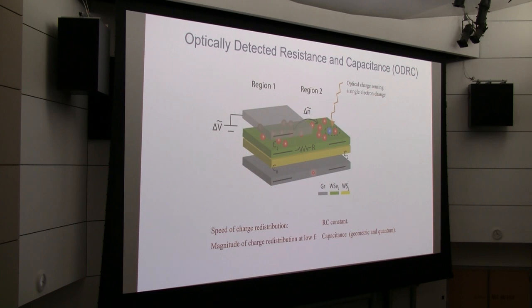And the idea is like this. We have two layers of transition metal dichalcogenide Moire superlattice, and we have both a top and bottom gate. The contact in the system is very bad, so it's hard to do transport, but it's still fine for us to just gate the material and change the carrier density. So once we can vary the density, and we have this partial top gate, what we can do is apply AC voltage to the top gate. As a result, because of capacitive coupling, the electrons in the 2D material will move around to respond to this gate voltage. And optically, we can actually measure the local electron density through its effect on the optical absorption.